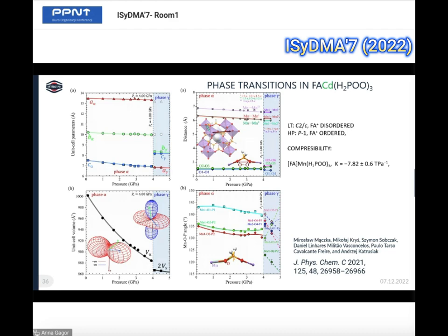And as you see here, the crystal structure of the hypophosphite is so nicely fitted to the ion at room temperature and zero pressure that we do not have a phase transition up to 4 gigapascal, which is for these organic-inorganic materials really high pressure.